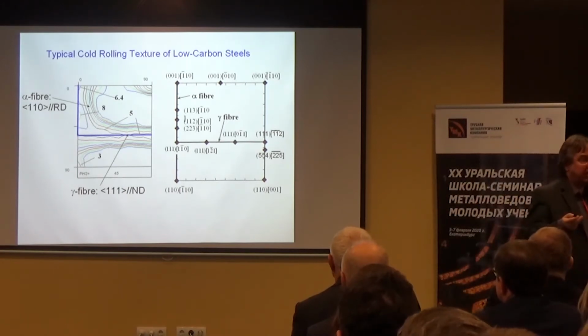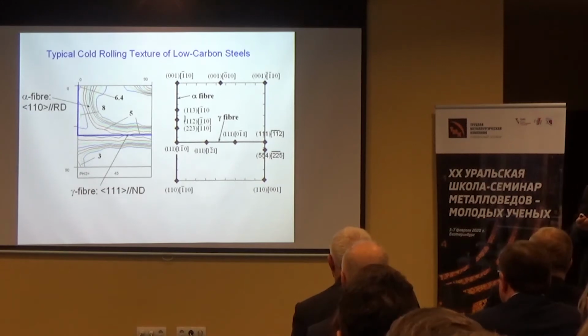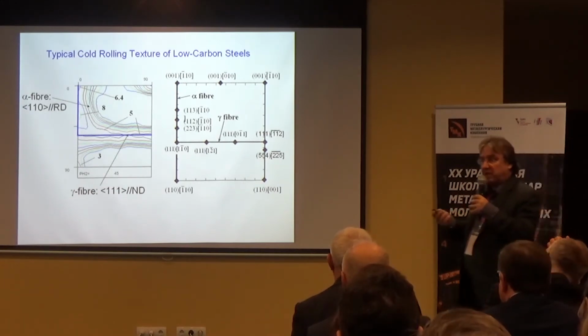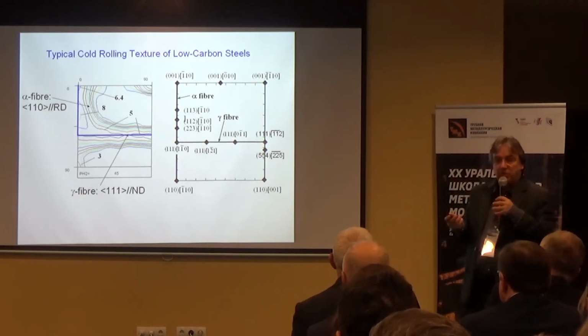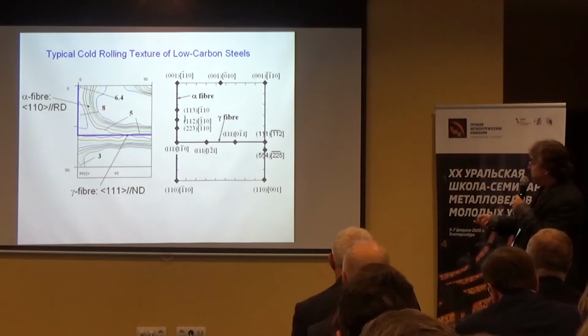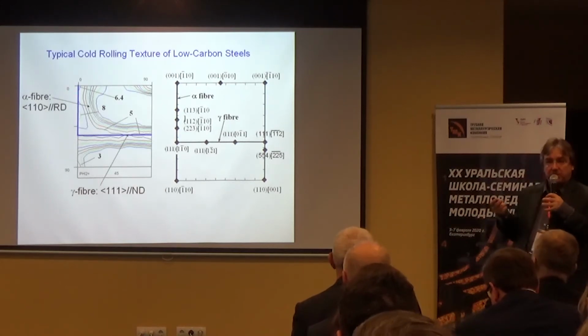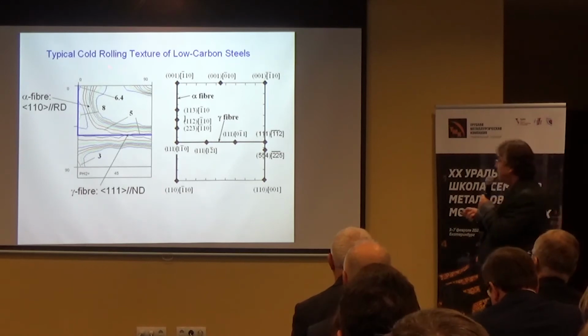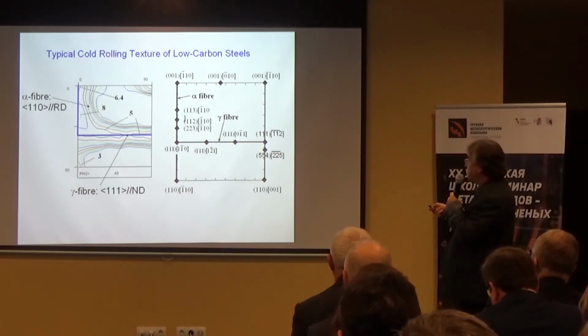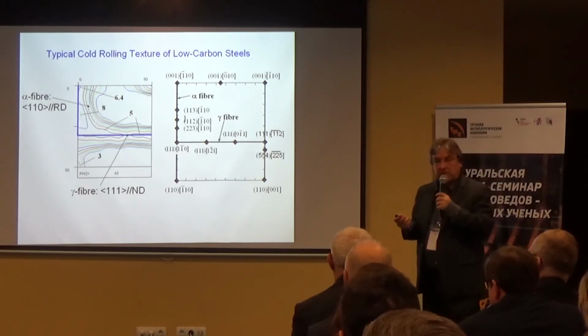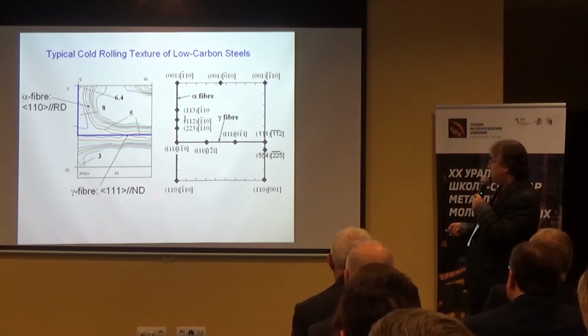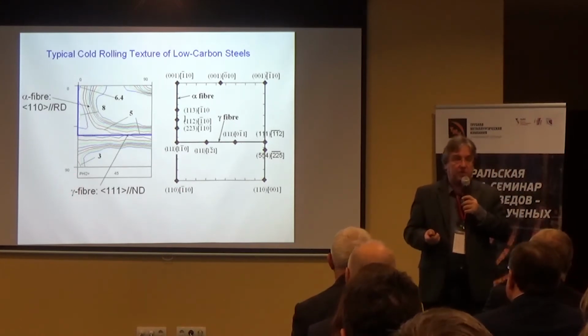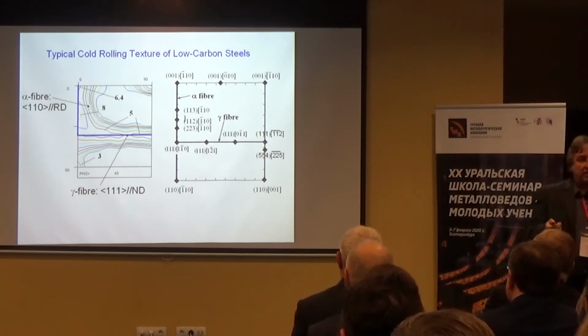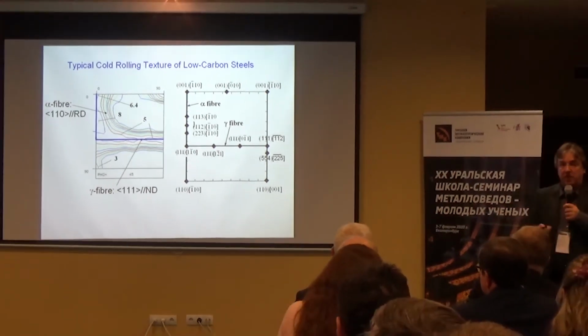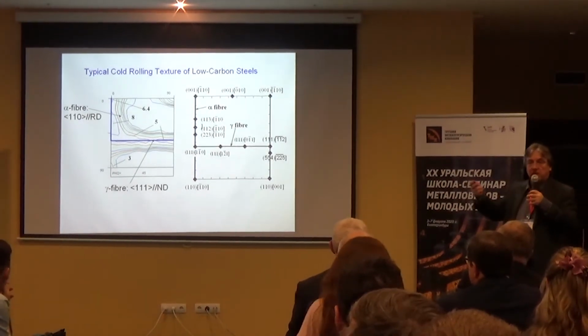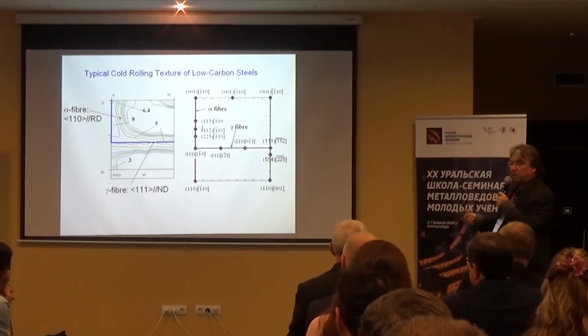Normally we represent textures with orientation distribution functions. These orientation distribution functions give you the intensity of the texture components in Euler space. So each point, normally it's a three-dimensional space. Fortunately, if you want to describe cold rolling and a typical cold rolling and annealing texture of low carbon steels with BCC crystal structure, we can do with one section of Euler space, the phi2 45-degree section. Why is this? Just by pure luck. Nature is favorable to us. So we don't need the three-dimensional description. We can just do with the two-dimensional section.